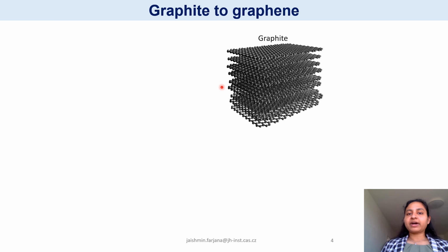But the problem with graphite is the capacity is less, and also this process of lithium storage in graphite is quite slow. So if we want to have a battery which has higher capacity and that can be charged very soon, maybe in a few minutes, we all want to have it, right? That is a bit difficult with graphite. So scientists tried to come up with other alternative materials which are capable of doing that.